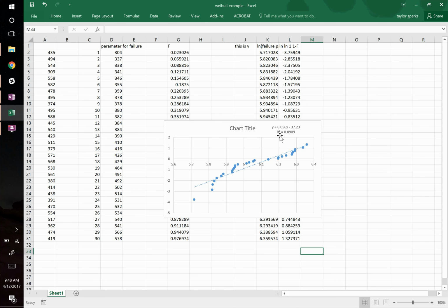So you can only do so much to get rid of flaws, but what you can control is try and limit the different types of flaws. And maybe the last thing you can't get rid of is porosity in your sample, and that's creating a critical flaw, right? As long as that's the flaw, then you should have a tight distribution because you're making it the same way each time. They should all be roughly the same size. If you have lots of variation in your processing, like in your plant, you could have all sorts of things going wrong that give you a much lower modulus and therefore a broader distribution.